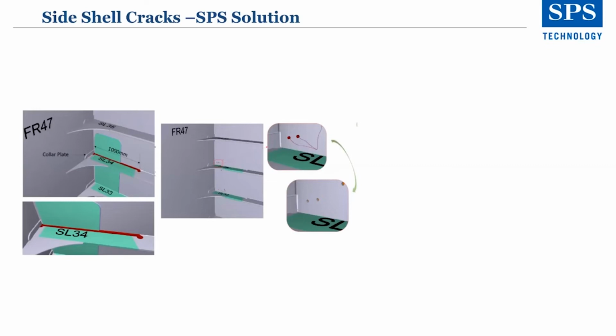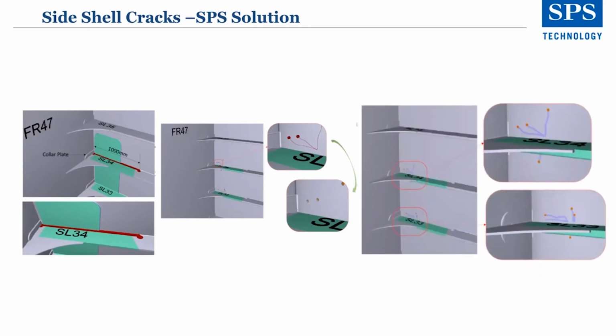Then we marked out on the longitudinal stiffener a line to be cut to try and remove the doubler to gain access through the temporary solution, to assess if the cracks had grown since the temporary solution was put in place. So we removed the upper doubler plate and lower doubler plate. In the center images, you can see we removed the wooden bungs that were in place at the aft end of the crack arresters. We fitted new brass plugs and we trimmed them flush to the side shell plating. We then ground the cracks to create a smooth open profile.